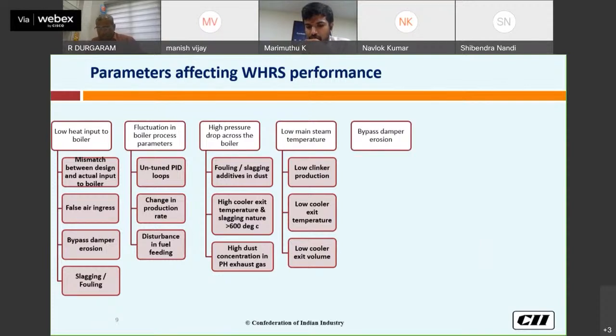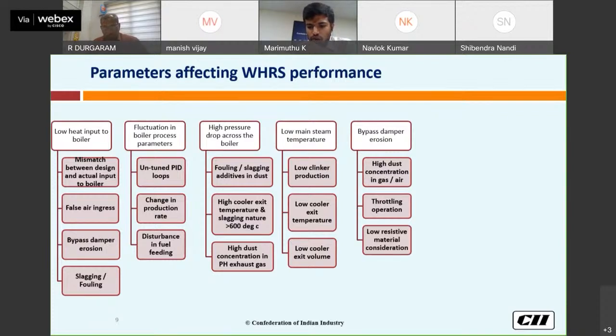Then another one is bypass damper erosion. The bypass damper erosion might be due to the high concentration in the gas or air, or due to the throttling operation. If you are operating the damper with slight bypassing, maybe 10% or 20%, then in that opening the velocity will be more, because the vacuum to the bypass damper will be more than the WHRS system. So it will suck more air from the damper only, which automatically increases the velocity and causes the erosion. And low resistive material consideration: during the design stage, if the damper is not designed with a high resistive material to take care of the dust, it will cause the erosion issue.